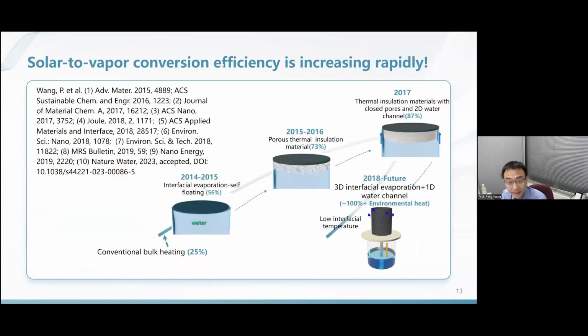Now, guided by the energy analysis I presented in the previous slide, this field of solar to vapor conversion has progressed very fast in the past 6-7 years. You can see here in 2014, the energy efficiency was only 25% with the conventional design. Then there was the interfacial heating design that boosted the energy efficiency to 56%. With the photothermal insulation design, 73%. And then when you separate the insulating material with the water channel, you got 87%.